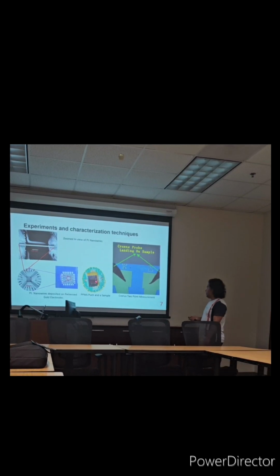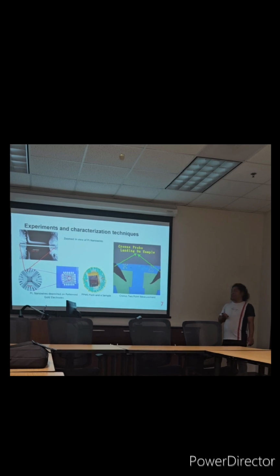And here in the middle, our black sample sits on top of the PPMS puck, Physical Property Measurement System puck. A close observation shows that this tiny gold wire runs from my sample to 4 terminals of the PPMS puck. This setup allows us to make measurements of electrical resistance at different temperatures.